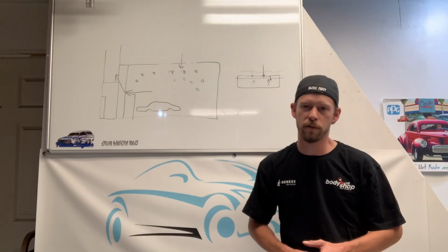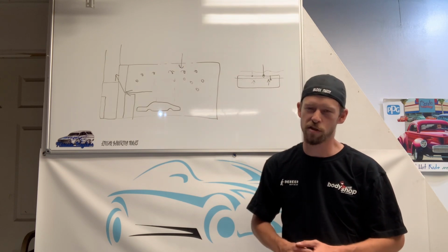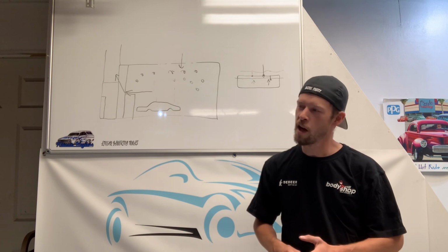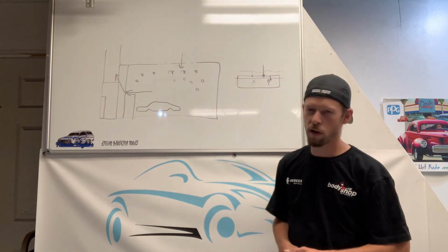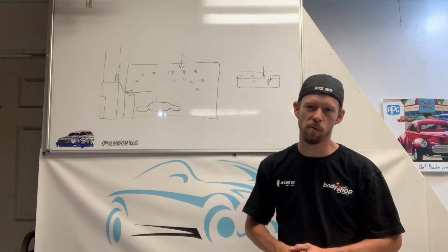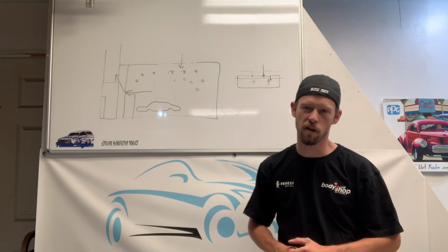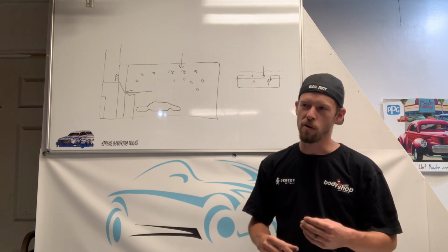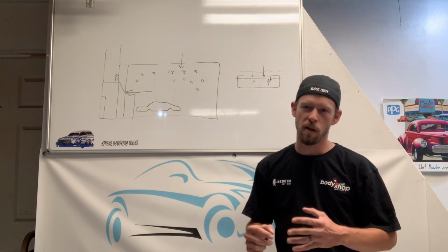I've heard of some guys talking about putting clear in the fridge and cooling it. That is a terrible idea. It may help with your solvent pop issue, but once your clear hits anything below 58 degrees, the isocyanates in it are dead, and once the isocyanates die, they will never come back. You won't have proper cross-linking in your paint system.